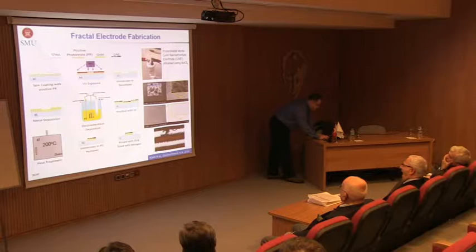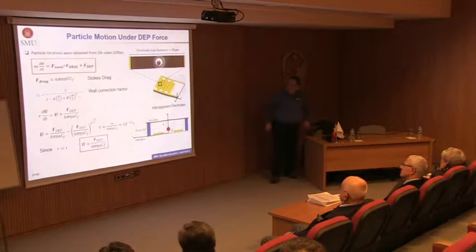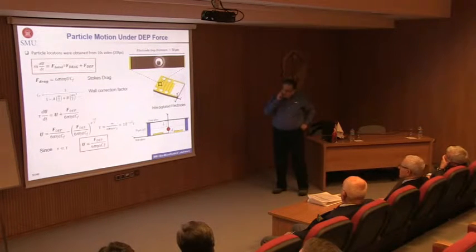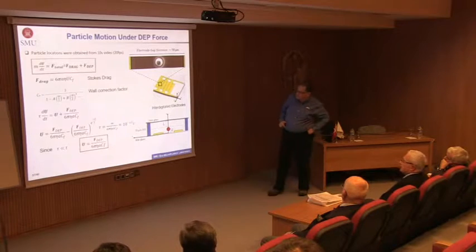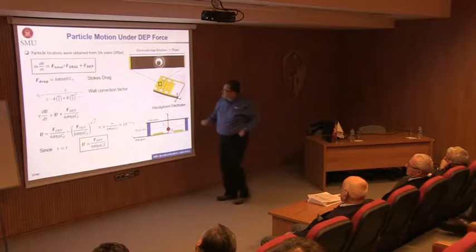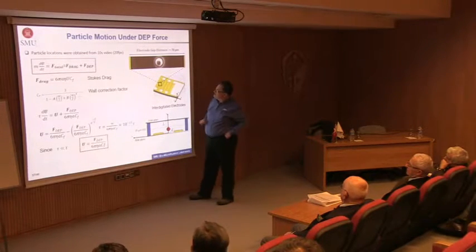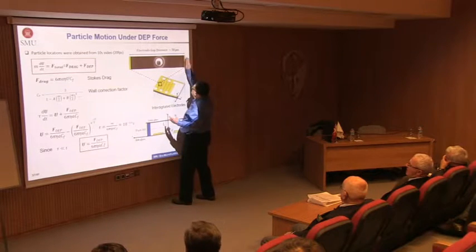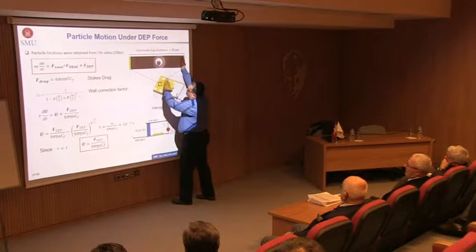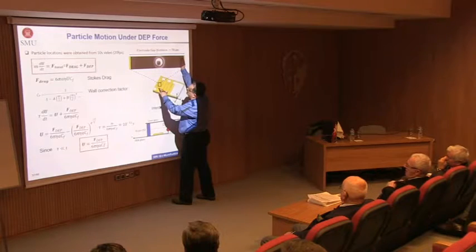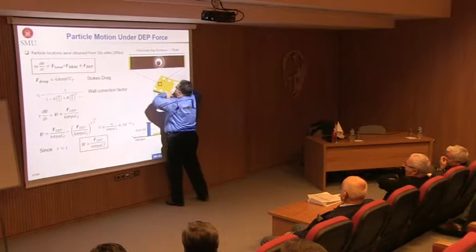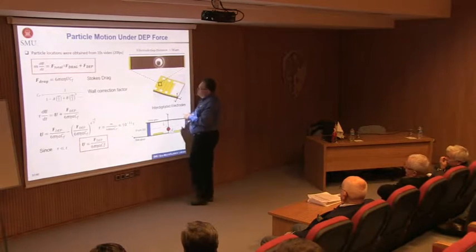And then we thought, what happens to DEP? Because it wasn't working very well in high conductivity medium. So we did these experiments with fractal versus planar electrodes. And the whole idea is this. I have this interdigitated electrode geometry, and this is the center of one of them, in between the two electrodes, and say this is one of the edges, and here's a picture of a cell.